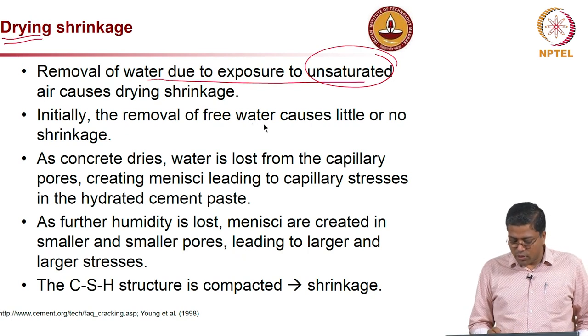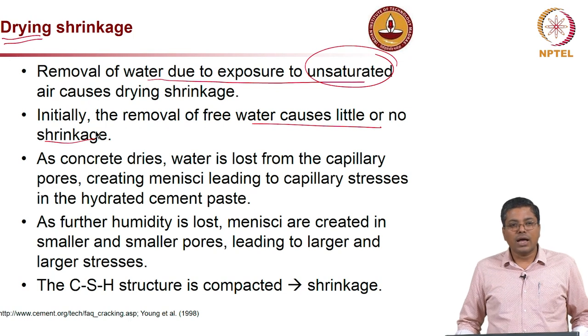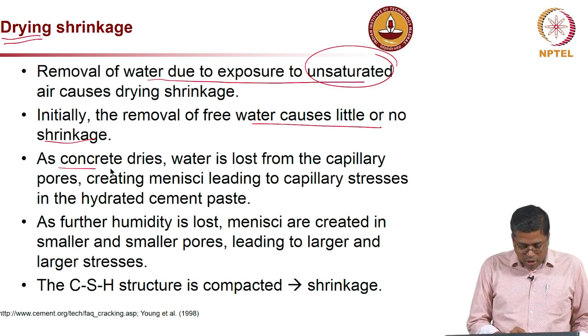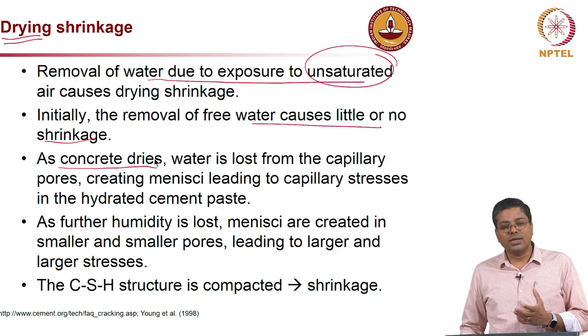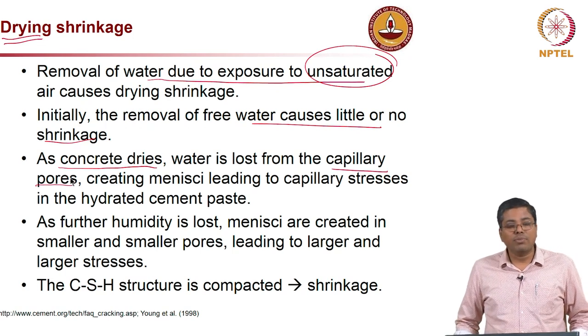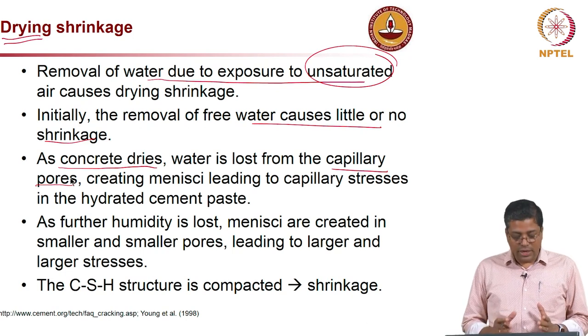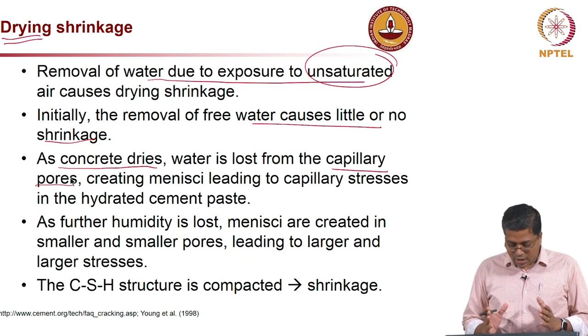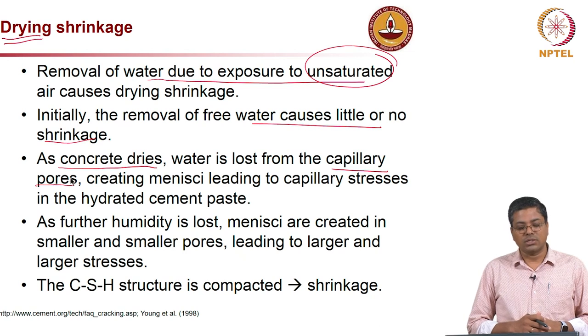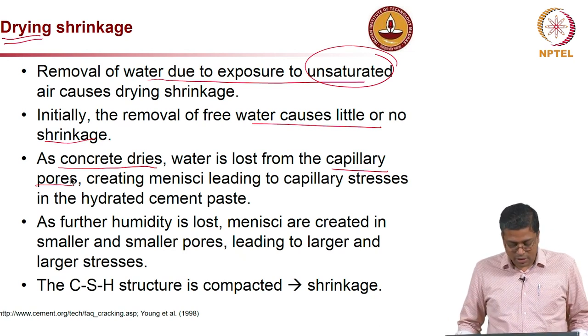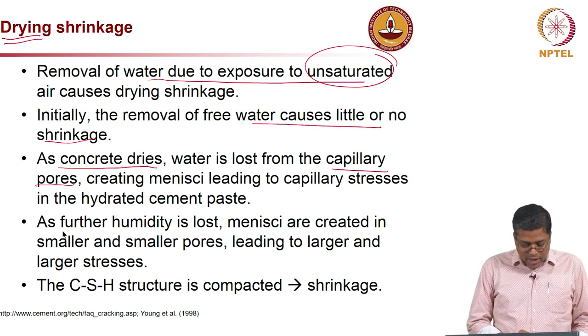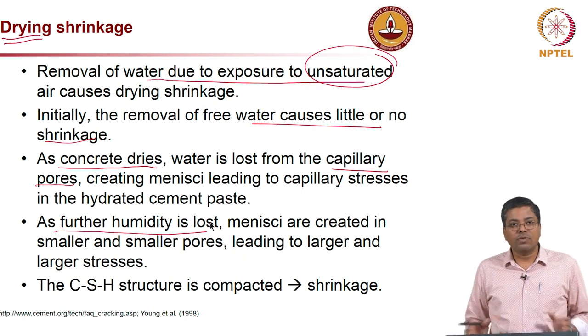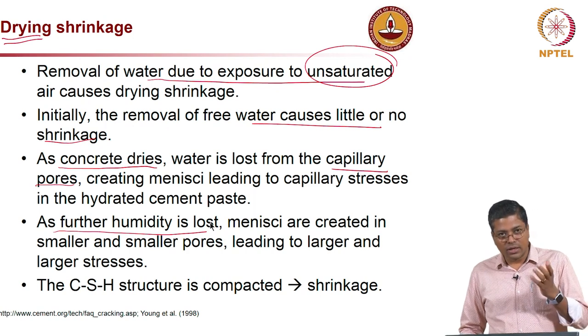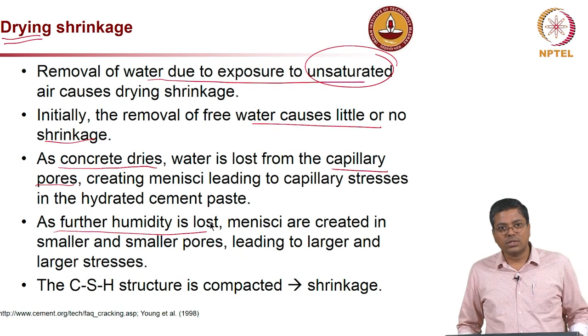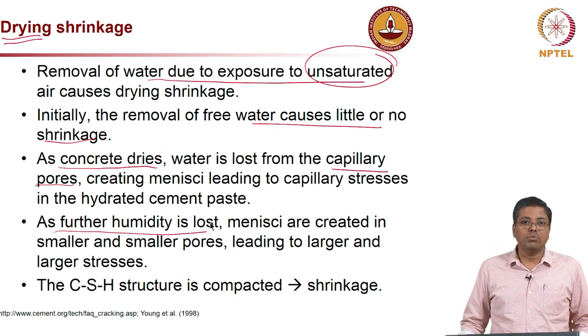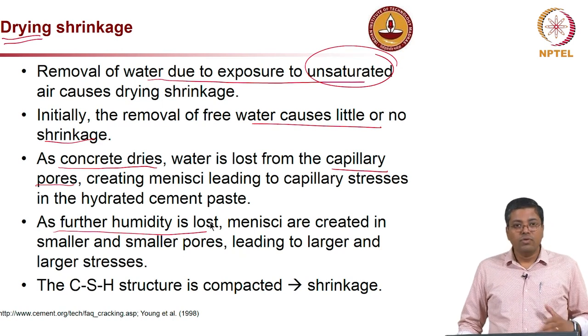And initially this removal of water does not cause much damage to the concrete. But as more and more water evaporates, or as more and more drying happens, the water present in the capillary pores is also lost. And what this leads to is that it forms menisci, leading to capillary stresses in the hydrated cement paste. Now, this can happen at multiple locations within the concrete, and as further humidity is lost, the size of these menisci is reduced, and when the size is reduced, that means the stresses are going to be more and more. So, the smaller the size of the menisci, the larger the stresses generated, which leads to shrinkage cracking.